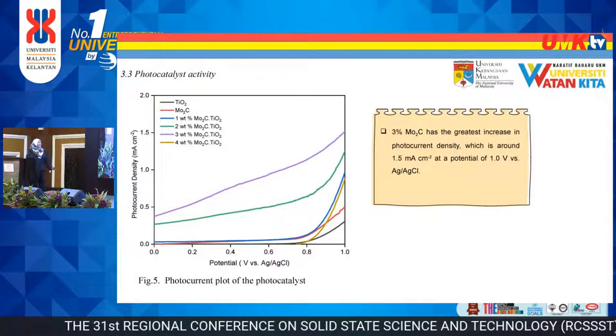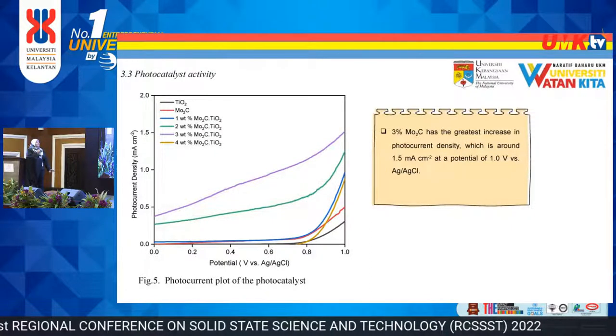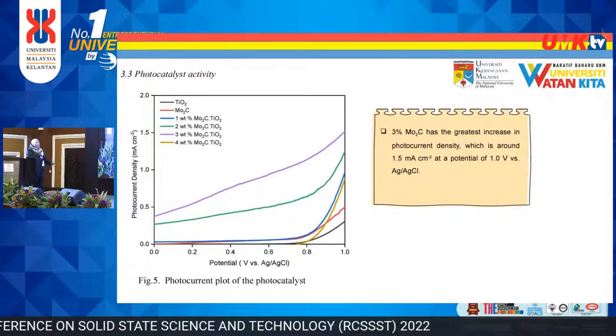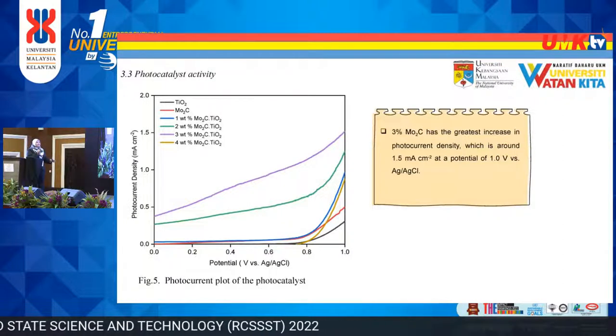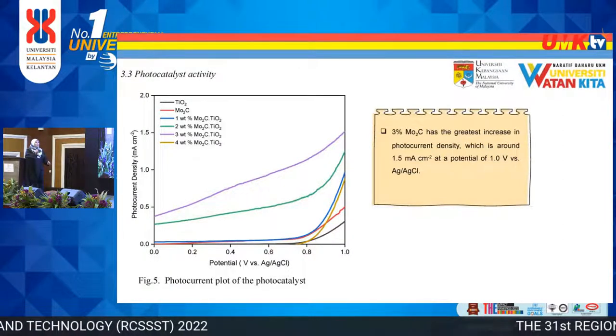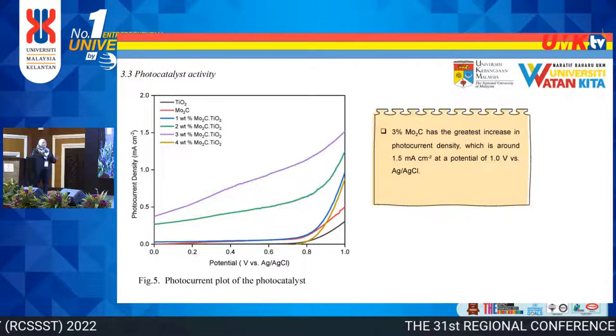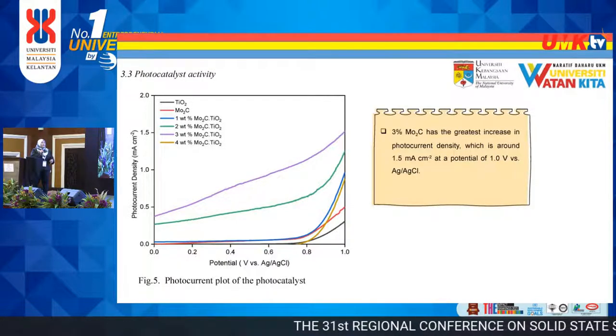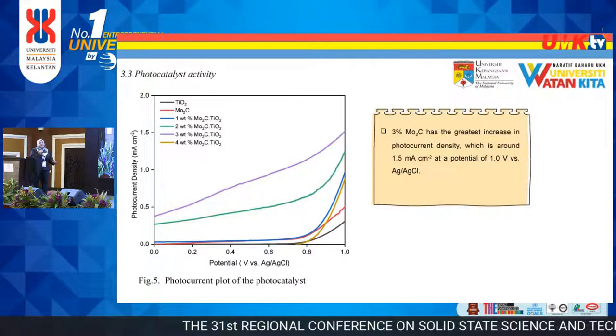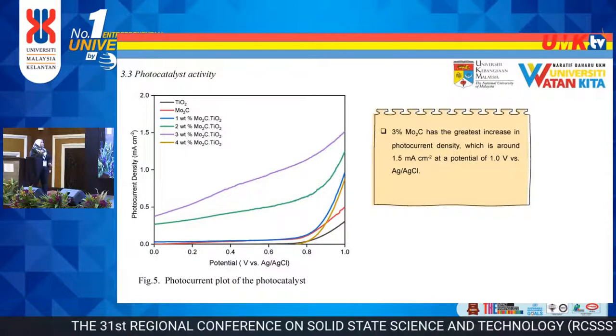So this is the photocatalyst activity measurement. Based on the measurement, it shows that 3 weight% has the greatest increase in the photocurrent density, which is around 1.5 milliampere per centimeter squared at a potential of 1 volt versus Ag/AgCl.